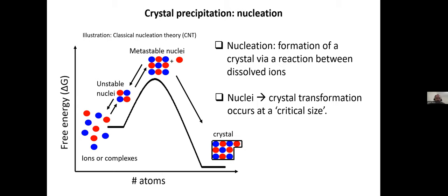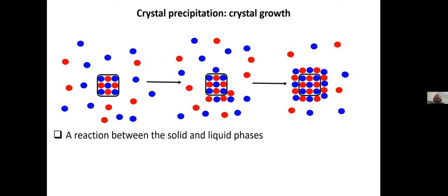Basically, if I have an oversaturated solution, there's an energy to be gained by creating a solid phase. This happens through the creation of small nuclei of the forming crystal. And due to interfacial tension, they're unstable. However, at a specific size, they overcome the interfacial tension and become stable crystals. So this happens at a specific size. This is something that's important, and I will address it again later on.